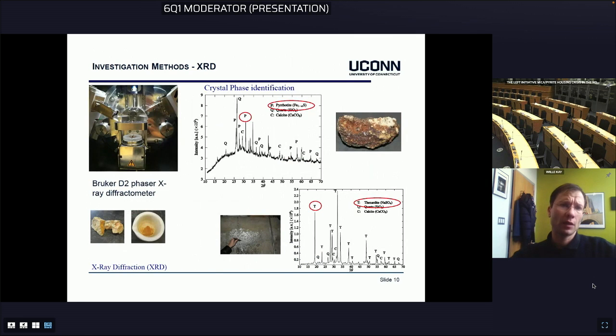The qualitative method, using, for example, XRD, you see here the equipment we have used, and the aggregate shown with the brownish discoloring indicating the oxidation of the pyrrhotite. It has been pulverized, and then this powder has been analyzed, and you see the crystal phase identification, and then with the software you can identify it's actually pyrrhotite in there. And also the white deposit in the lower picture had been scraped off the wall and analyzed for crystal phase identification, and you see that, for example, pyrrhotite was present there in a high amount, and this is sodium sulfate.